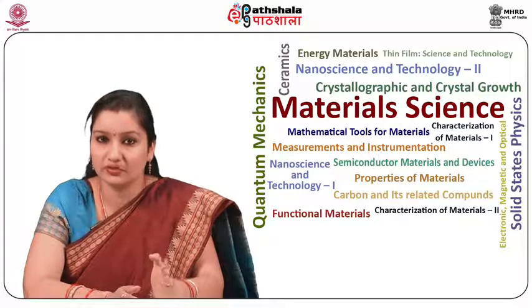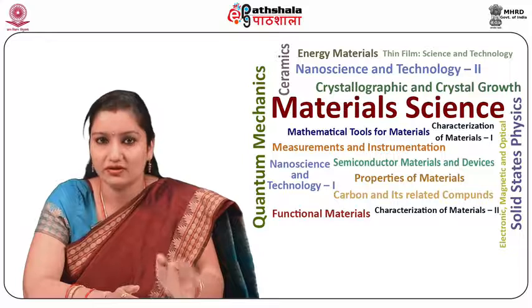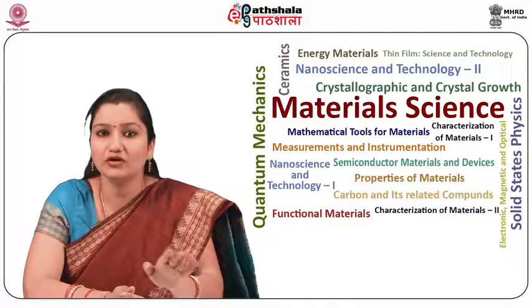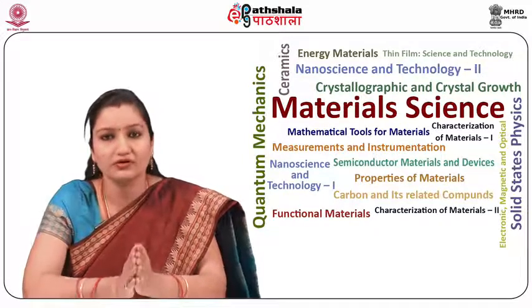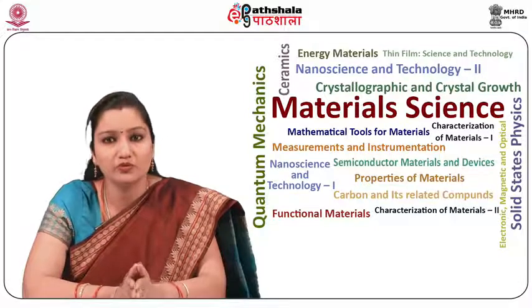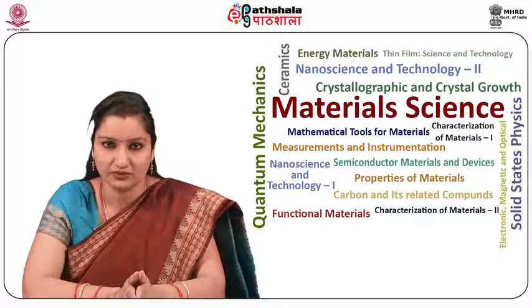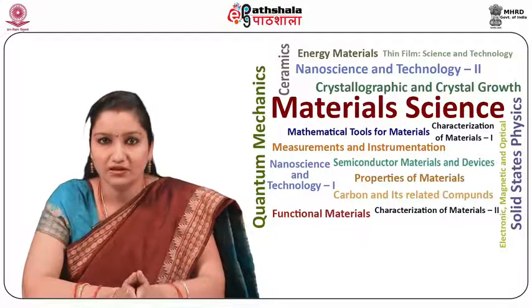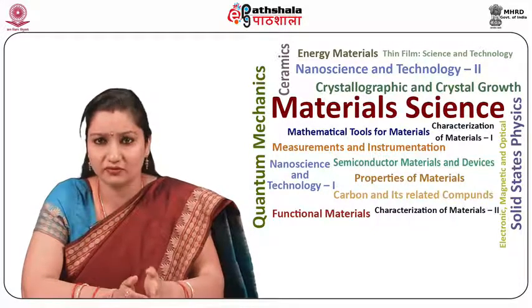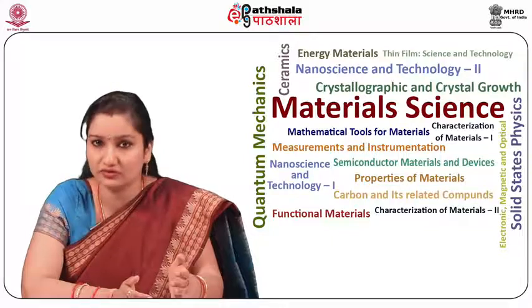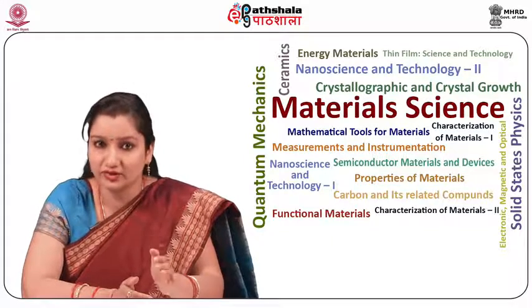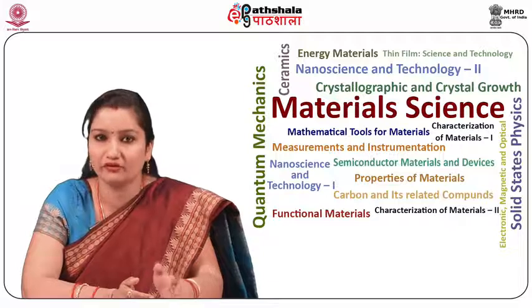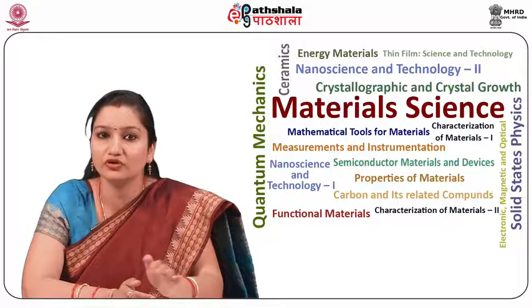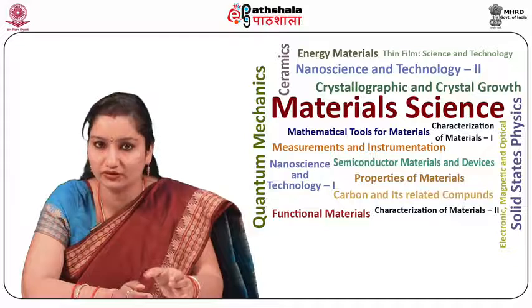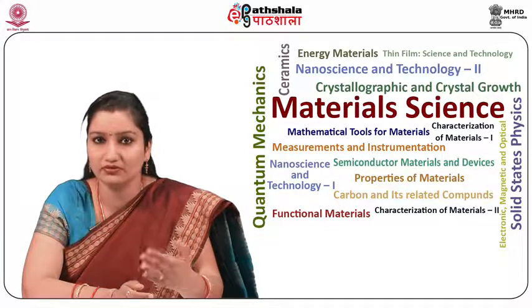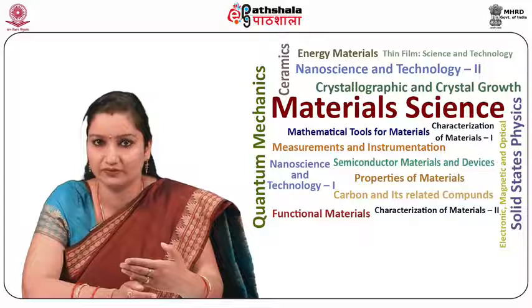For long time durations at low stresses, the fracture is similar to brittle fracture because of negligible deformation produced in the process. That is, we can divide the stress times into higher stress and higher temperature, then higher stress but shorter time and moderate temperature, and the third one is long duration stresses which are low in magnitude, and depending on them the fractures are of different types.